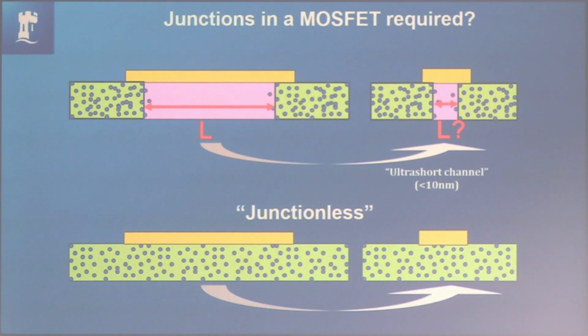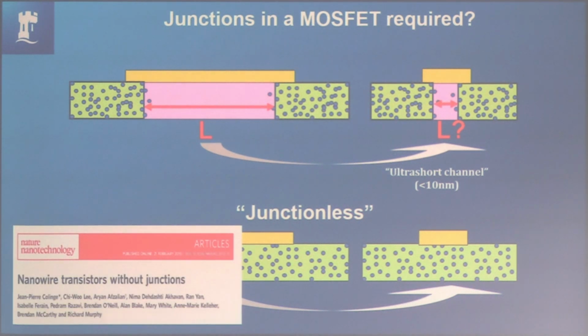And he did it, they made them, and they work quite well. They made P and N type transistors, but these were on a few tens of nanometer or less scale. Why didn't they do that in 1960? Why bother with making junctions? The idea is quite simple. If I have a heavily doped piece of silicon and I try to gate it, well, if it's metallic, the screening length isn't going to go very far.